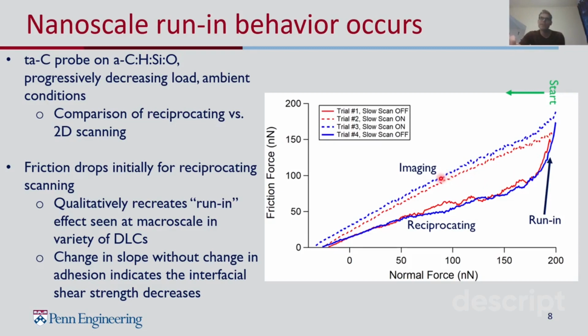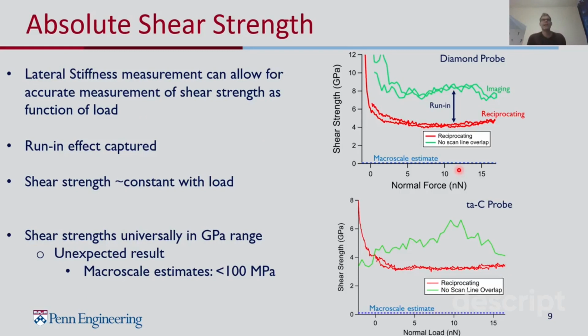And so it seems like the parameter to be interested in here is the interfacial shear strength. And so given that, we want to actually know what the interfacial shear strength is. An advantage of the nanoscale measurements is that we can actually measure that and calculate it. And the way we do this is by doing something called a lateral stiffness measurement, where we oscillate the tip laterally and measure the force response. And from that force response, we can actually calculate what the real area of contact is. And since we know the friction response and the real area of contact at a given load, we can calculate the shear strength at any given load. And so what's done here on the right, in the case of two different probe materials. So in the top case, we have a hard diamond probe, and in the bottom case, we have a tetrahedral amorphous carbon probe. And in both cases, the response is quite similar. So what we see is when we compare the imaging mode, we have a much higher shear strength than we do in the reciprocating mode.